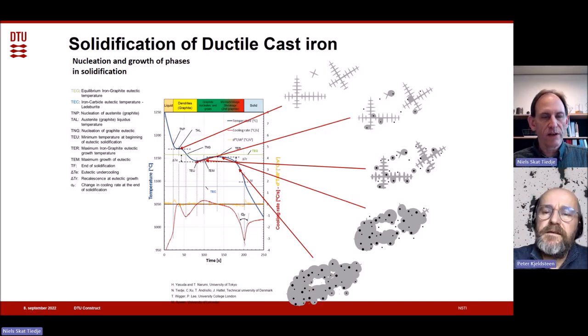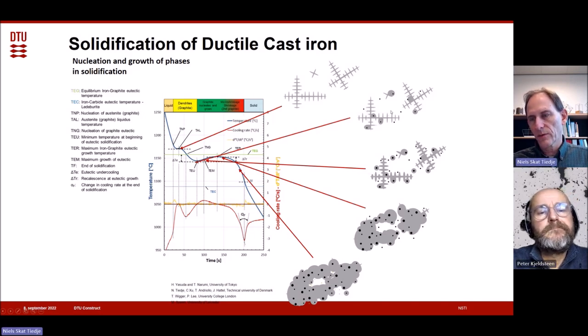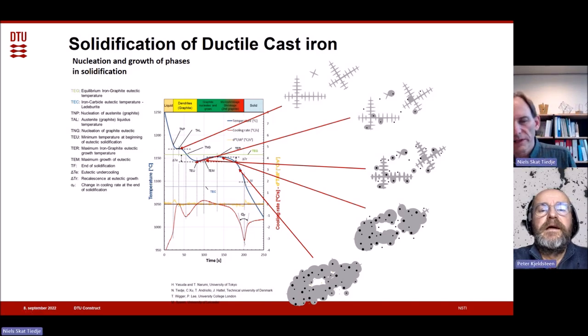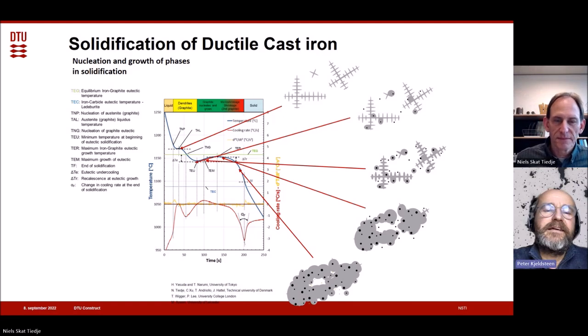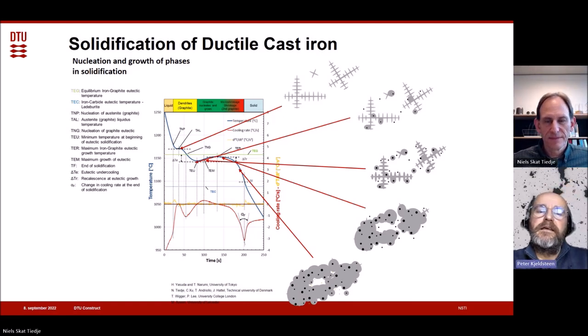And we also know, because it's a dynamic process, we have an undercooling relative to what's predicted by the phase diagram. Then we have graphite, black dots, forming, and we have austenite forming around those. We get gradually more and more graphite and austenite as we follow the cooling curve until the point where everything is solidified. And when looking at the curve, it goes up again. The temperature goes up again.